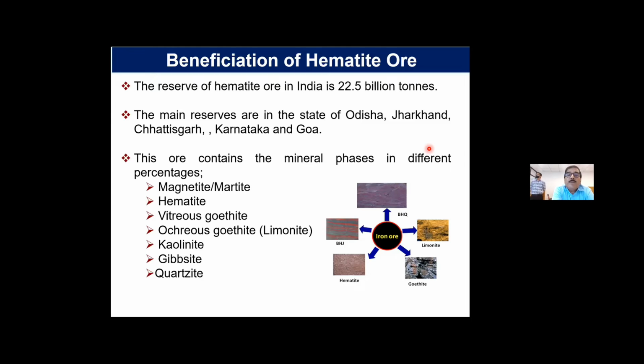In your hematite ore, normally they don't believe the magnetite is there, but it creates a problem for beneficiation, particularly for those using high intensity magnetic separators. That's why you have to take care before putting the ore into high intensity magnetic separation. You have to use either LIMS or MIMS to protect the HGMS. Otherwise, HGMS or WHIMS will choke.